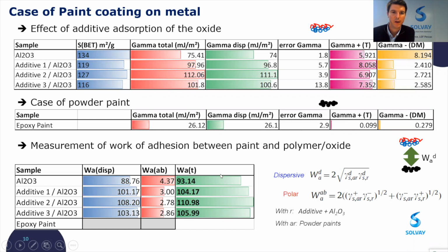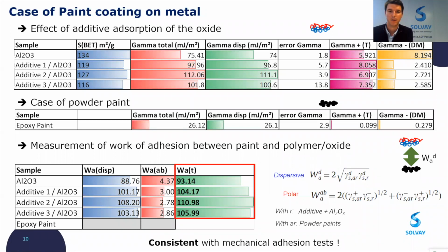As you can see here, we can see an increase of the work of adhesion when we have some additive at the surface. So it's very consistent also with application tests, and especially with mechanical adhesion tests, we see a better performance when we have the additive. This is the goal of the additive.